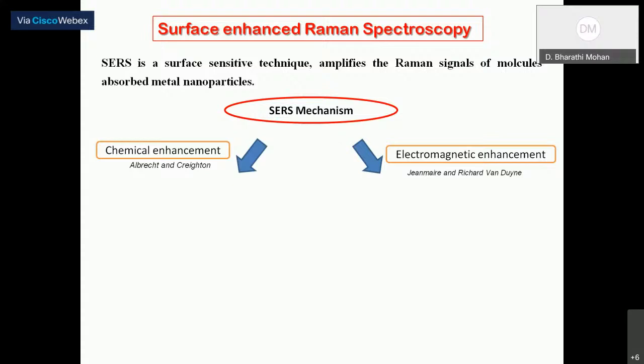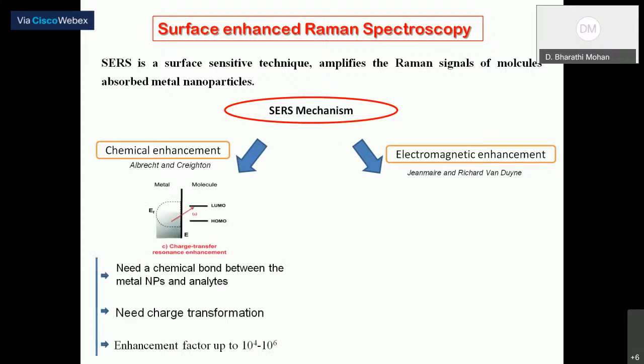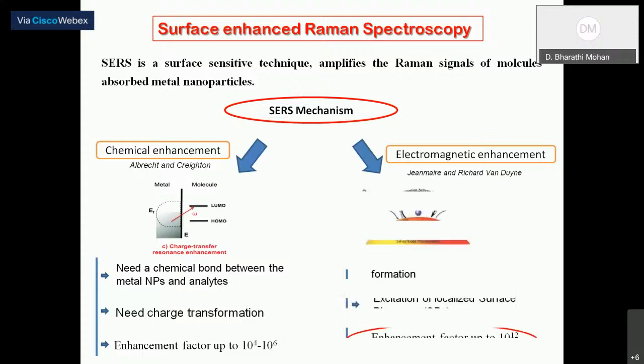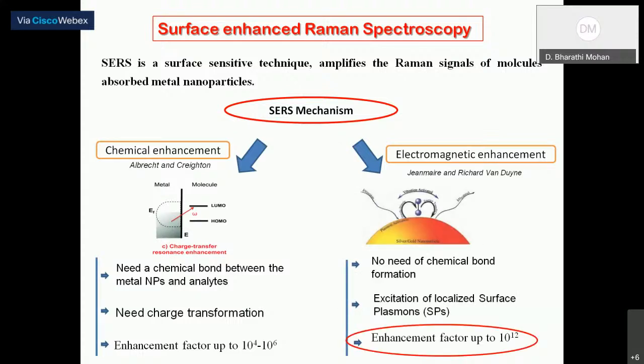What is chemical enhancement? Chemical enhancement requires a chemical bond between the metal and the analytes. So when the metal is bonded with analytes, there is a charge transfer from the metal to the molecule, and the charge transfer enhances the Raman scattering of the probe molecule. On the other hand, electromagnetic enhancement does not require any chemical bond formation, and the Raman scattering of the probe molecule is enhanced through the excitation of localized surface plasmons. If you compare the enhancement factors, the enhancement factor for electromagnetic enhancement is much higher.